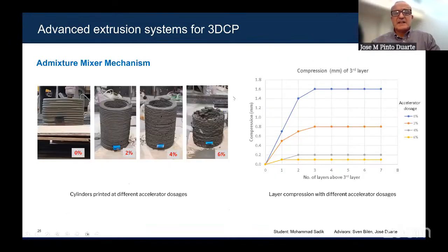And then the other capability is to add the admixture. There are different types of admixtures. One can be an accelerant. What the accelerant does is reduce the time for the material to get hard. If you do that immediately before extrusion, the material retains good flowability properties while it's going through the hose. And then once it's extruded, it will harden very fast.